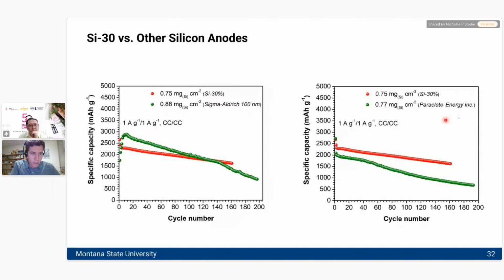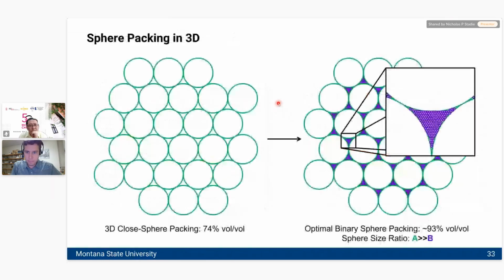And when we talked to companies making pure silicon anodes, the only commercial operation that would actually send us electrodes was this company Paraclete, and their material that had around the same loading as our material was significantly performing worse. So we were really happy with these results, and we think particle mixing is probably an underexplored area, especially in silicon, but maybe even in other aspects of battery electrochemistry.